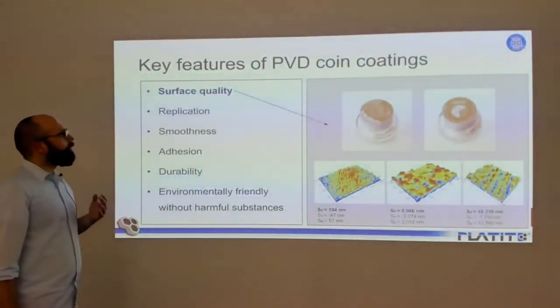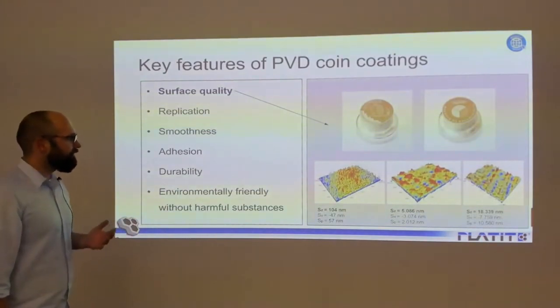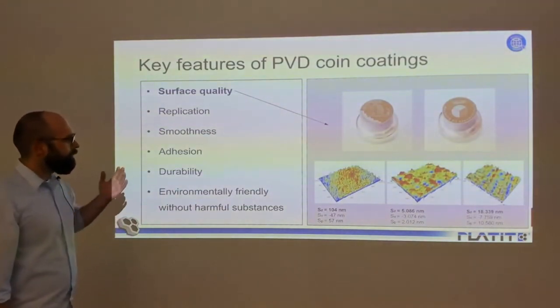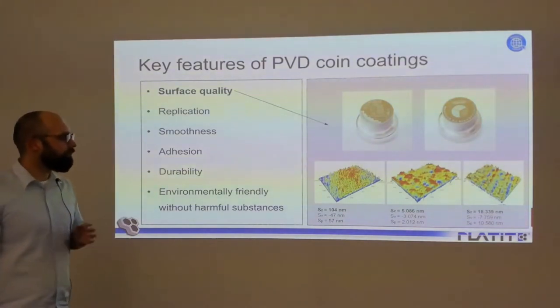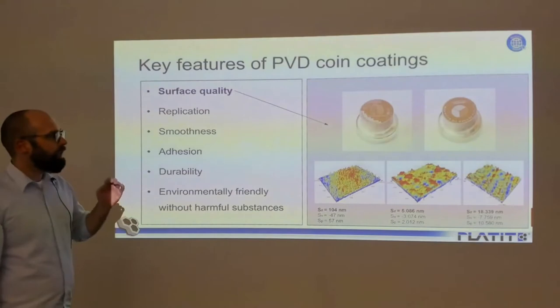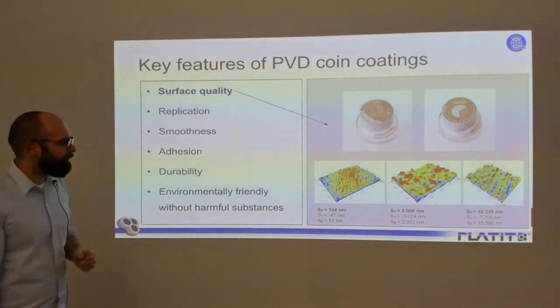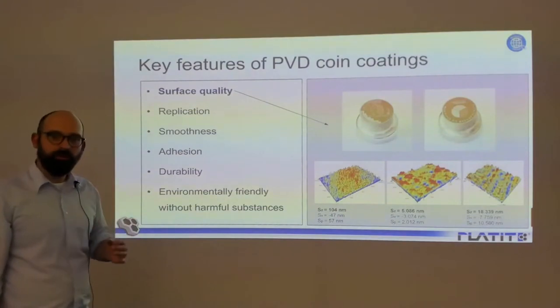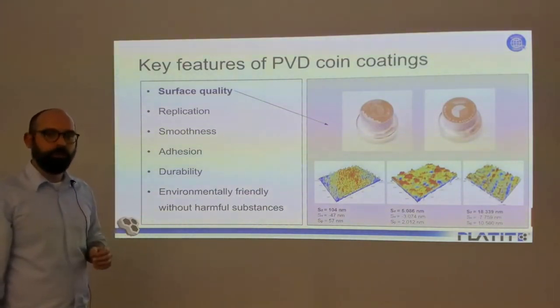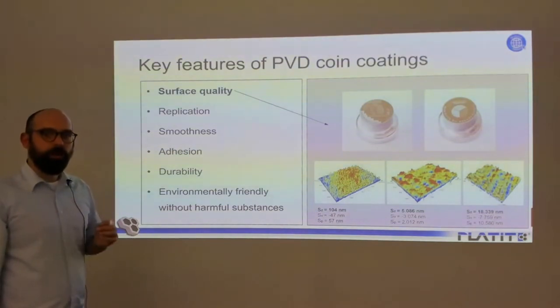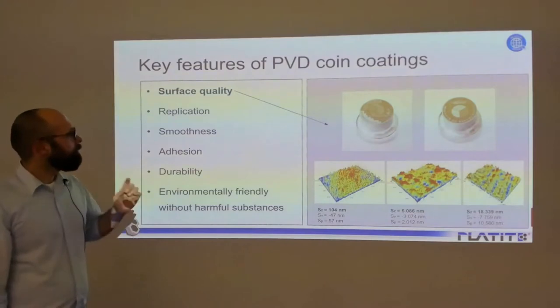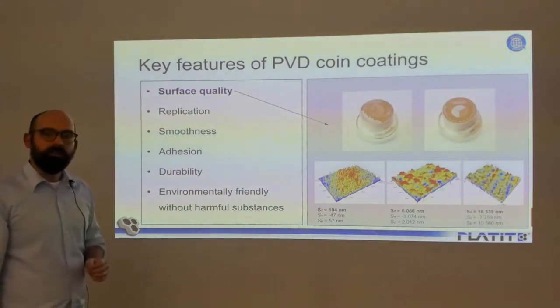Well, if you look at a coin stamp, the first thing that really strikes is the tremendous surface quality. We have mirror polished areas with roughnesses in the order of a few hundred nanometers. And within the same stamp, we see micro patterned areas where we have roughnesses in the order of several thousand, yes, even up to several ten thousands of nanometers. That's more than one order of magnitude difference in surface roughness. And with the Platit S-Impulse, we are able to perfectly replicate and copy this surface with a 2.5 micrometer thin chromium nitride layer.